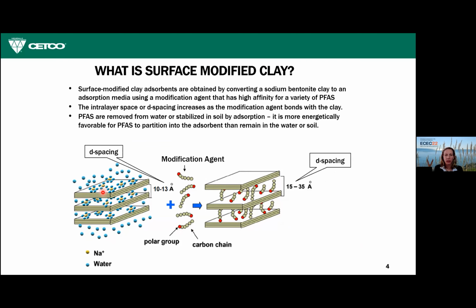When we react the modification agent shown here with the clay, it replaces the cations and water in the intergallery space and makes the clay basically hydrophobic so that it does not swell when contacted with water. And this is a phenomenon that can be tracked by something called the d-spacing, which is measured in the laboratory with an X-ray diffraction scan. It's a pretty basic measurement. The d-spacing for bentonite clay is 10 to 13 angstroms. And when you have the surface modification, the d-spacing increases to 15 to 35 angstroms.